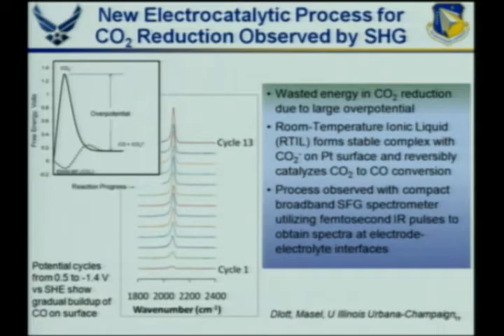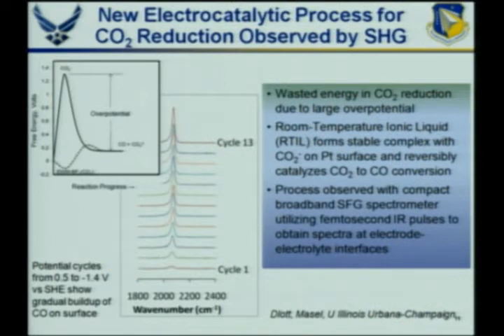So again, this species of CO2 minus is a key here. That's this key intermediate where we can get the CO2 to start reacting with things. And it turns out if we use an ionic liquid, which now has ionic species present, it can help stabilize this CO2 minus on an electrode surface, reducing this overpotential tremendously to make this now a possible mechanism. But again, this mechanism was very speculative. So Dana Dlott in our program developed a very interesting compact spectrometer taking advantage of something called sum frequency generation, which looks at molecules that don't have centers of symmetry, or molecular systems in which there's no center of symmetry.